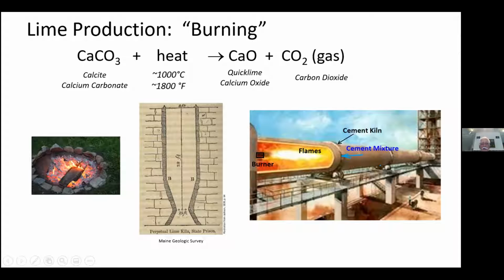Then occasionally you can tap into the lime which has been produced down at the bottom, down in here. Over on the right is a modern cement kiln. A lime kiln will look the same way, in which you have a large rotating drum which carries material up into a progressively hotter zone and basically burns it that way. And then the whole thing is automated. You can produce immense amounts of material relatively quickly in that way. But the basic process is that you're heating the material up, producing quicklime, calcium oxide, and releasing carbon dioxide gas.